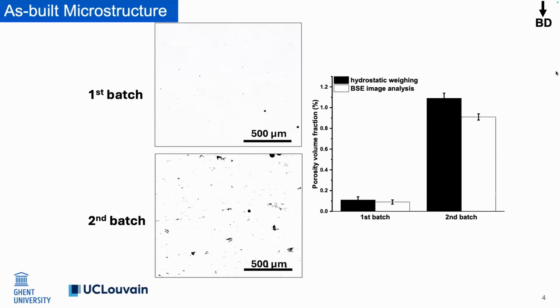So, preliminary results. First, you can see the cross-section of the first batch and second batch, and the first batch shows a porosity fraction of almost 0.1%, and the second one shows almost 1% porosity fraction.